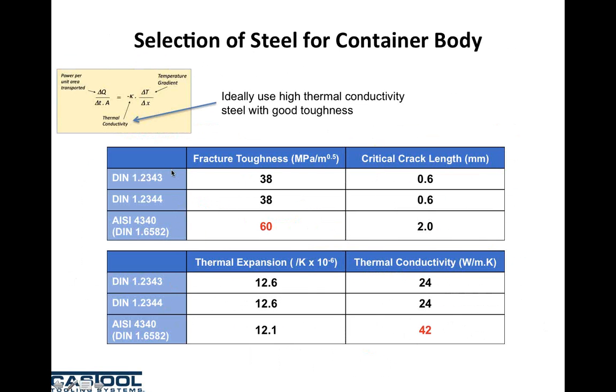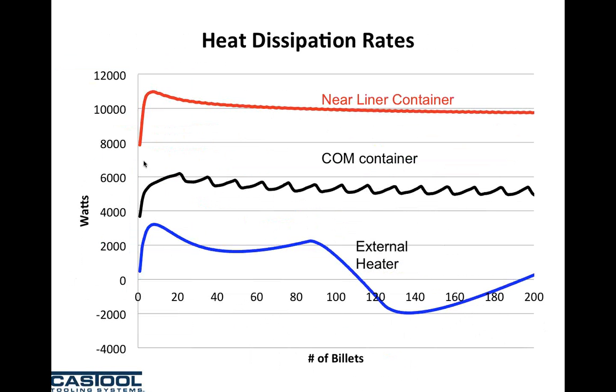And what's interesting, if you couple the thermal conductivity and temperature gradient together, you see when you put the heater close to the liner, you see the temperature gradient multiplied by the right material, 4340, compared to if you put the heater at the center of the mass with the conventional H13 material, you see the heat dissipation rates are vastly different.